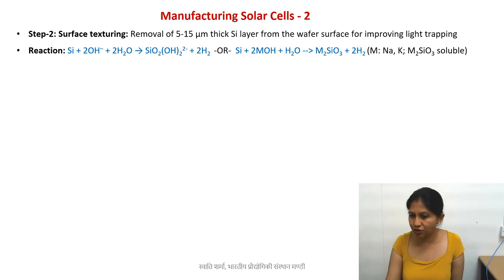In the industrial process, etching is always done using basic solution. Basic etch has high pH, above 9, and with very concentrated solutions we may have above pH 12.